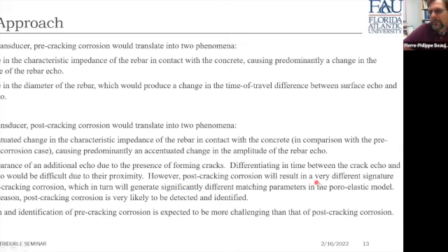However, post-cracking corrosion would also result in a very different signature from pre-cracking corrosion, which in turn would generate significantly different matching parameters in the Poro-Elastic model. And for this reason, when it comes to the level of difficulty, post-cracking corrosion is much more likely to be detected and identified than pre-cracking corrosion would be. So we are focusing right now on differentiating between a virtually perfect sample with no corrosion and what a sample would produce when early signs of cracking are taking place. Again, detection and identification of pre-cracking corrosion is expected to be more challenging than that of post-cracking corrosion.